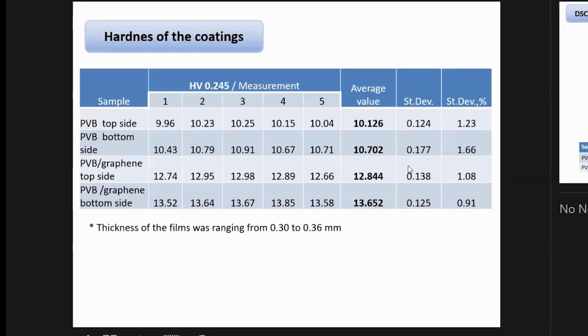Then the results of hardness of the coatings are shown from both sides of the coating. We have tested the hardness on the top side and the bottom side when we took our composite samples out of the Teflon molds, because the results were different. So we wanted just to point out that at some point, after the ethanol evaporated during the solidification of our composite films, part of the graphene sedimented on the bottom. So we have somewhat bigger hardness from the bottom side than from the top side of the composite coating samples. And of course, as expected, we have higher values for the composite samples containing nanographene platelets.